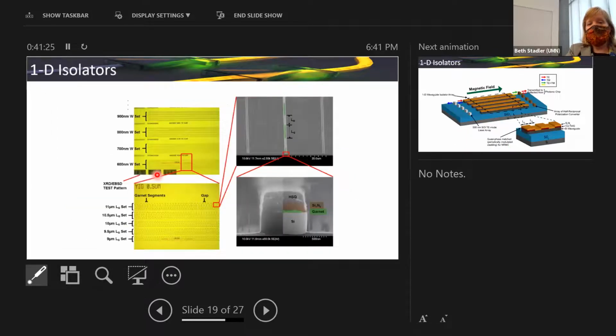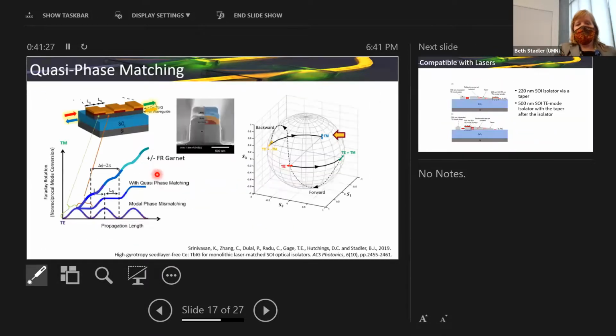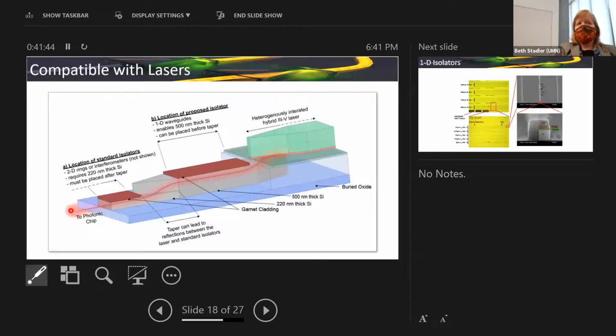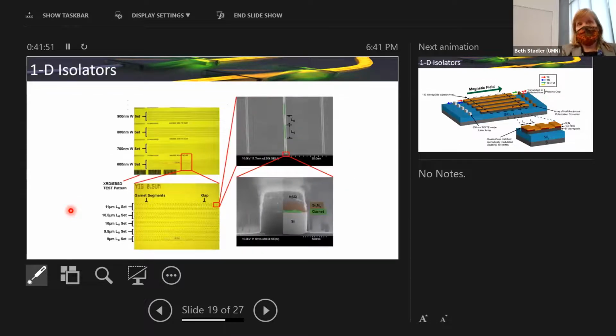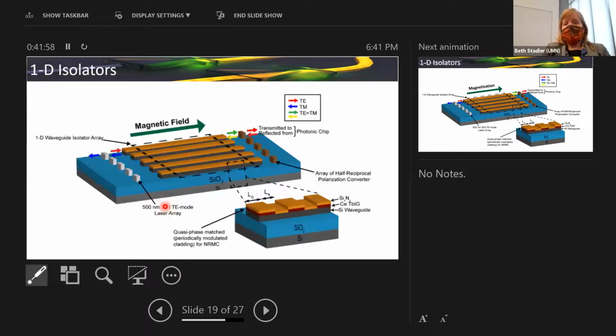So on 500 nanometer, which actually, I'm sorry, it was this core right here, it also turns out that this beat length is pretty long, because your waveguide is so isotropic that we ended up with a beat length of like 22 microns. So you need a certain number of them, but it's not so much. 22 microns is very easy to make with photolithography, at least let me say it that way. So you don't need E-beam lithography. We did use it with David Hutchings in Glasgow to make this structure. And we're just trying different beat lengths to see what we got.